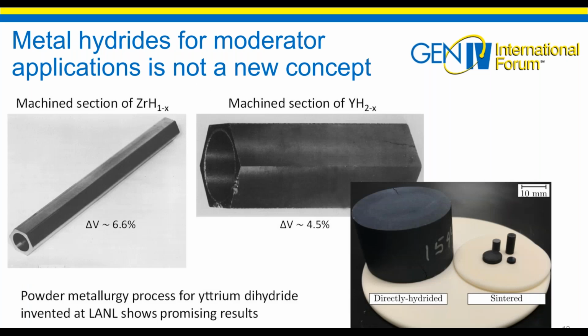Metal hydrides that are being considered in the microreactor program have been machined in the past, as shown in the pictures below, both for zirconium and yttrium hydride. Different techniques exist for the fabrication of yttrium hydride, including direct hydriding, which is well known and shown on one of the pictures to the left, and powder metallurgy, which is a promising new technique that produces stable material with fewer cracks, as shown by the sintered material to the right.